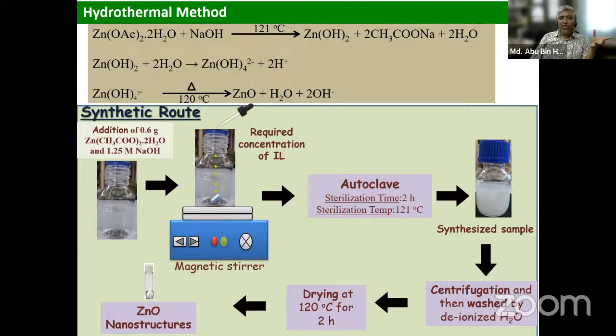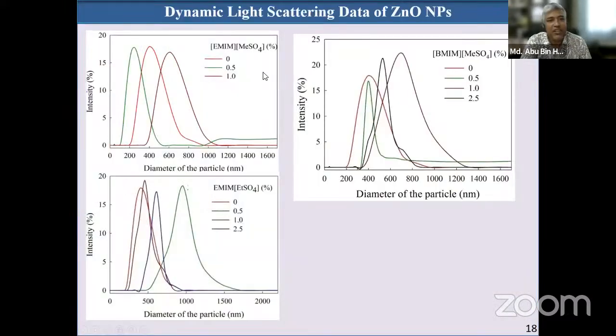So in an autoclave, at elevated temperature, in fact 121 degrees centigrade was found to be sufficient. After sterilization of 2 hours, we could synthesize zinc oxide nanoparticles, and after centrifugation and drying, we could finally have zinc oxide nanostructures. At a glance, we first checked by dynamic light scattering, by photon correlation spectroscopy, and you can see the diameter here.